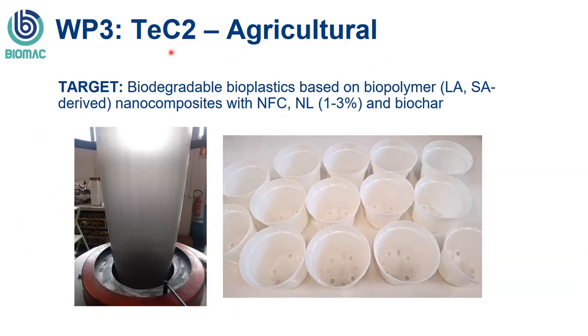And in this case, the idea is to come up with biodegradable bioplastics, again, based on polyester type materials. So lactic acid is here, succinic acid is here. These are being used to produce different kinds of polyester formulations. And we are using additives to further gain performance in this context. So nanofibrillated cellulose, of course, is something that you can imagine might be useful as a mechanical performance additive. Nanolignin, that's NL, right, can be used to give you, for instance, antioxidant activity. And biochar, for instance, which is basically a carbonaceous bio-based material, can be used to give you a deep coloration to block UV and visible light and things like that.